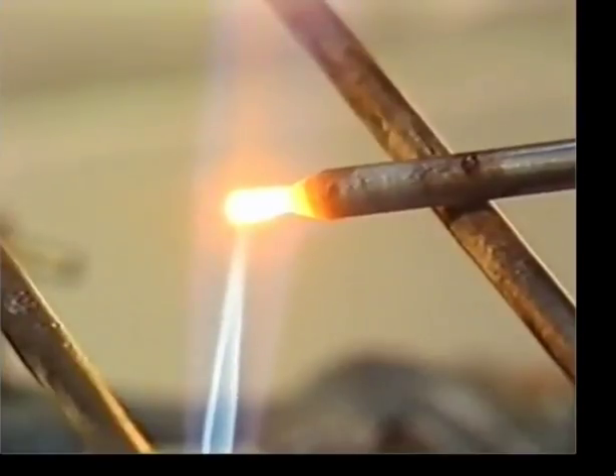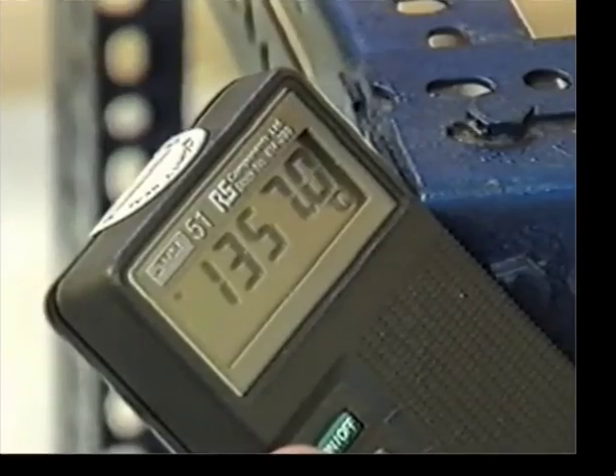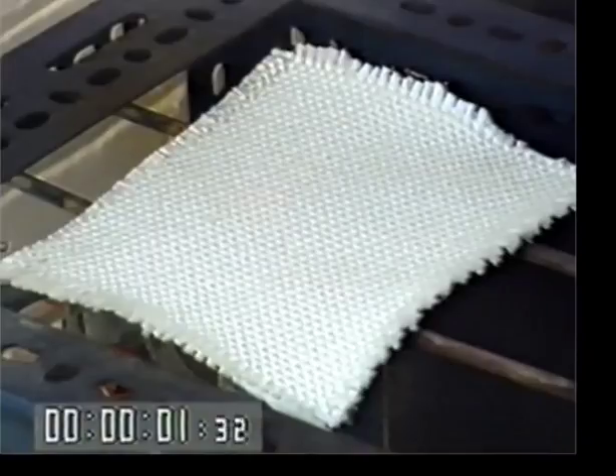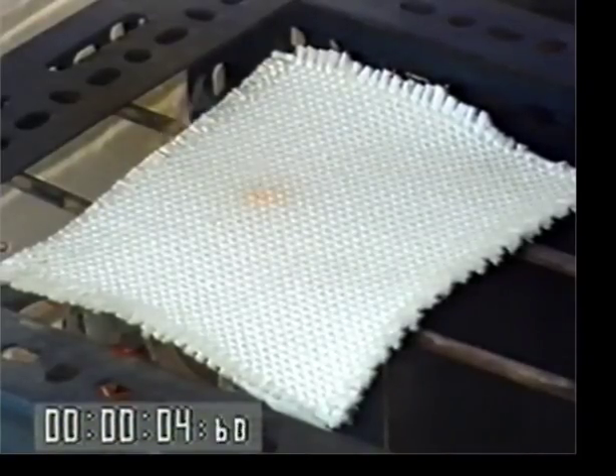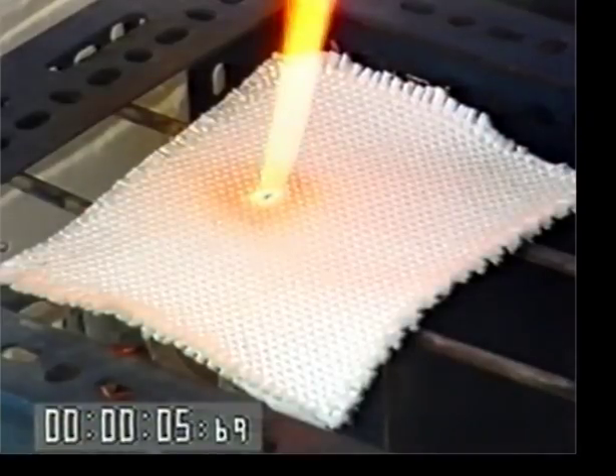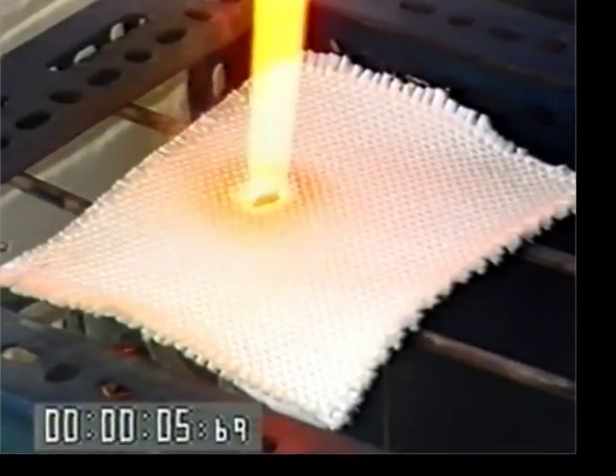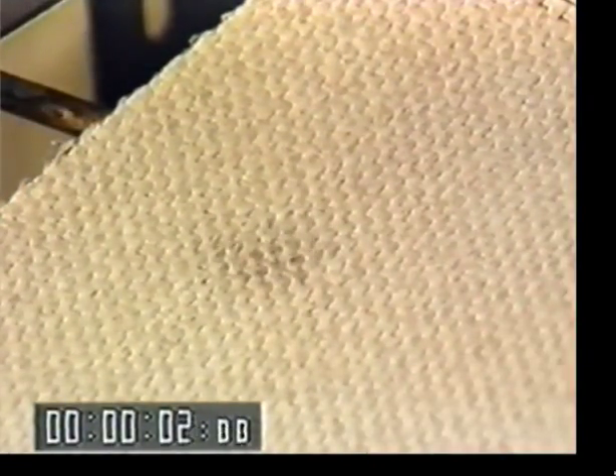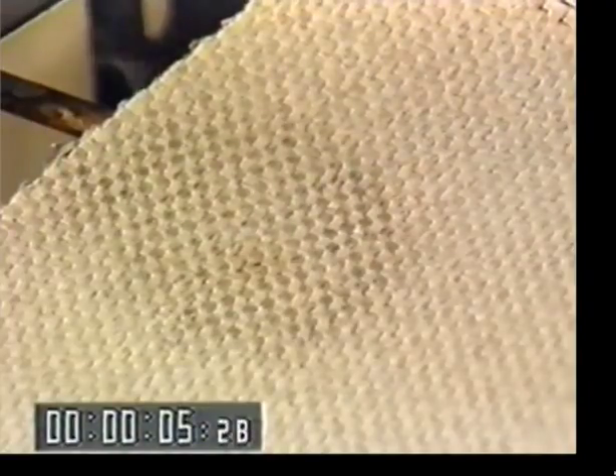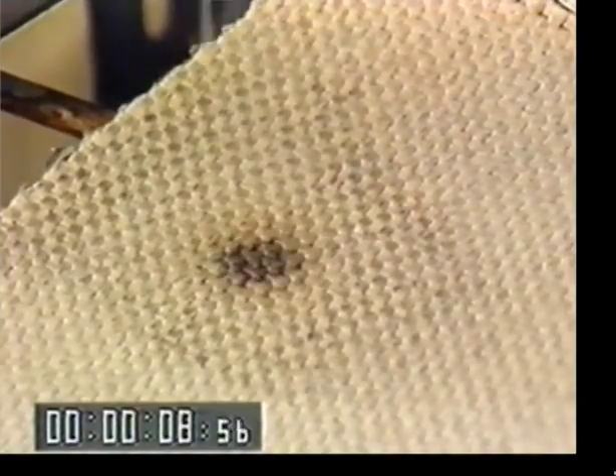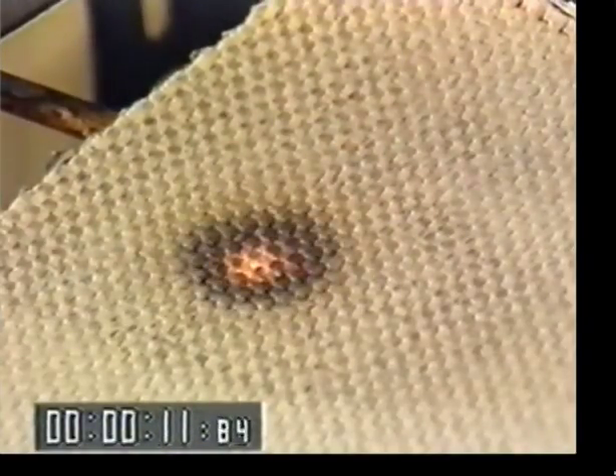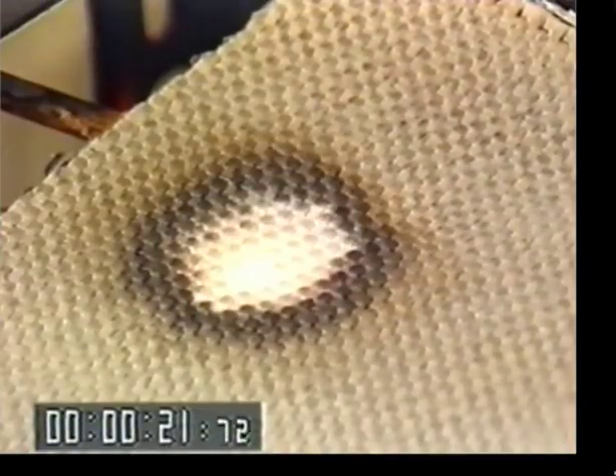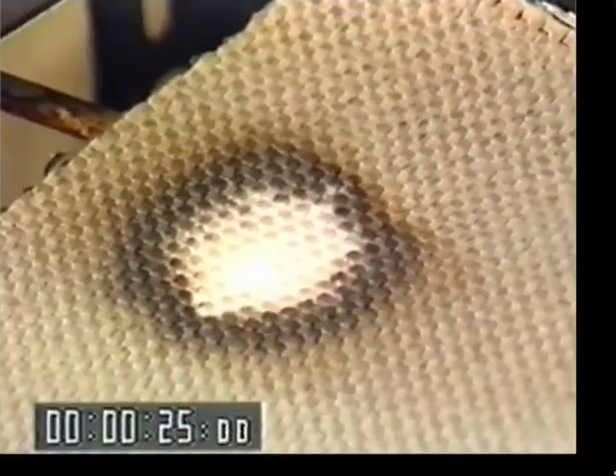Another test compares the performance of Weldstop fabric and untreated glass fiber cloth when each is exposed to oxygen-enriched gas flame at 1,350 degrees Celsius. Within 6 seconds, the untreated cloth has failed. Weldstop fabric of the same weight and thickness retains its integrity for almost 25 seconds. Each of these tests has been independently monitored and verified by the Shirley Institute, a world authority on textile technology, behavior and performance.